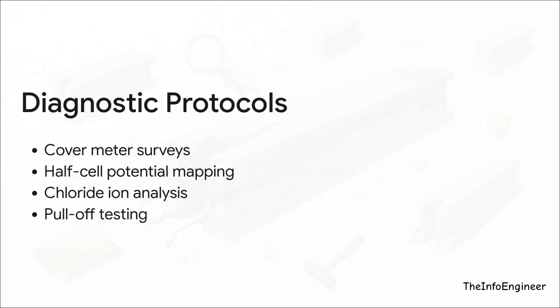But what happens when an older structure is already compromised? Well, engineers don't just guess. They use rigorous diagnostic protocols. They use cover meter surveys to map out the exact steel depth. They use half-cell potential mapping to find hidden electrochemical corrosion activity before any physical cracking even appears on the surface. They drill dust samples for chloride ion analysis to check for pitting corrosion, and they do pull-off testing to make sure the remaining concrete is actually strong enough to hold a repair.